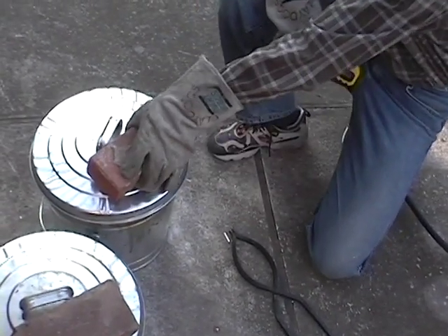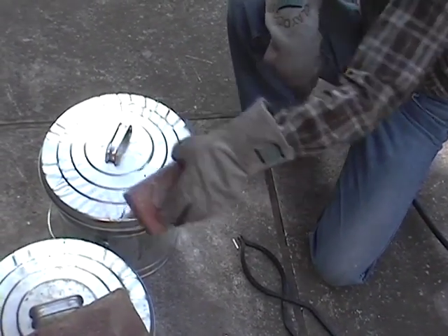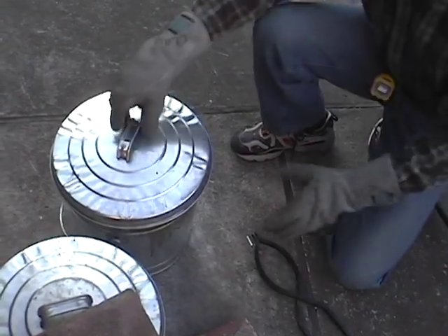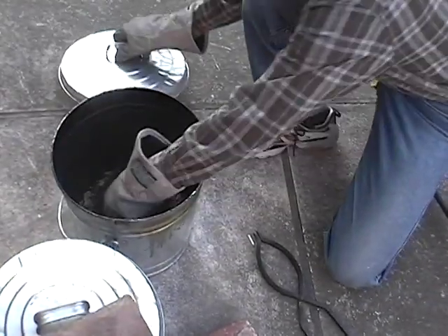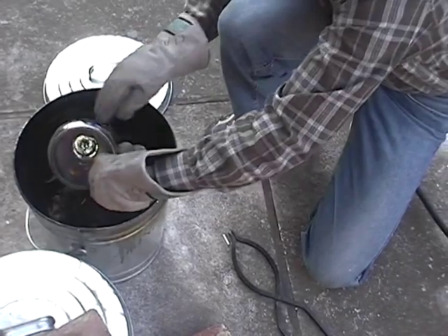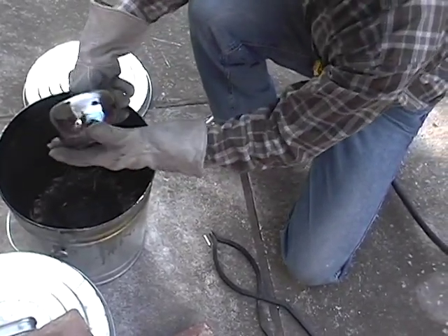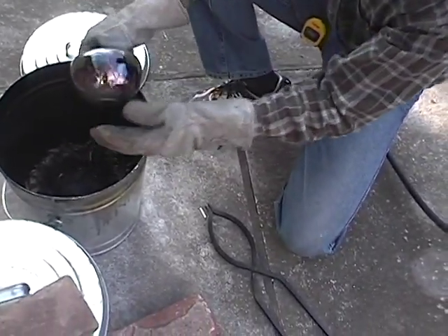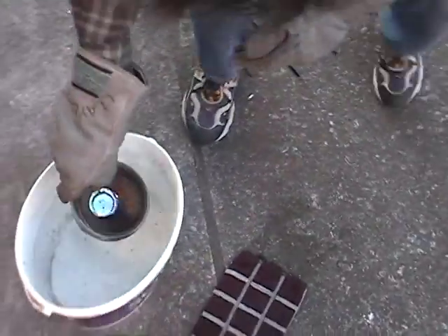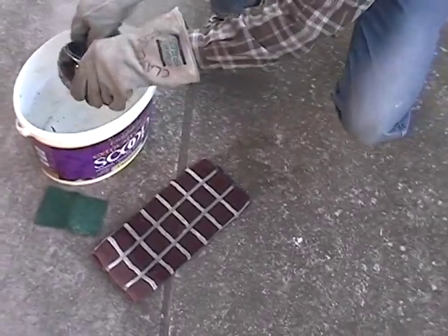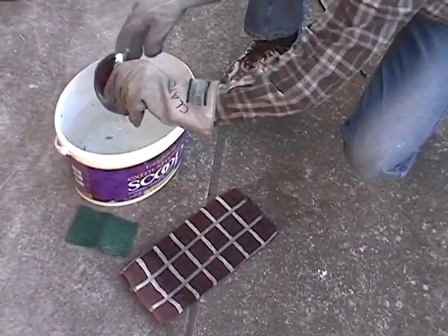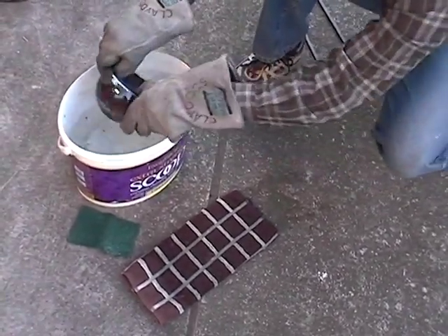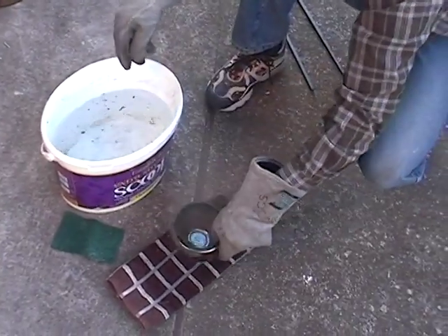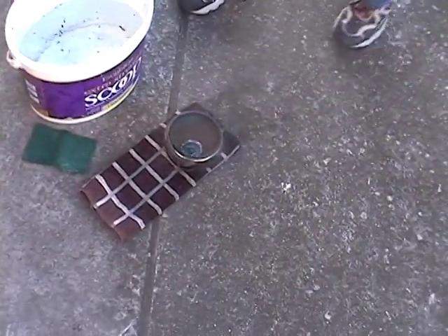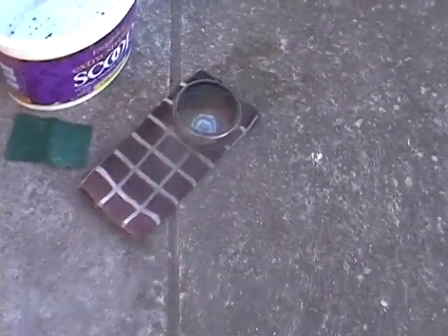After about 15 minutes, you can take the brick off and open up the can to see the result. Smaller pieces should have cooled to the point to where you can actually handle them with the leather gloves. Here we have an interesting copper effect that occurred due to the reduction of our actual turquoise glaze. I'm going to freeze that copper effect by simply dunking the piece in water. Due to the temperature of this particular piece, dunking it in water could fracture or bust the piece. That's part of the risk of doing raku.